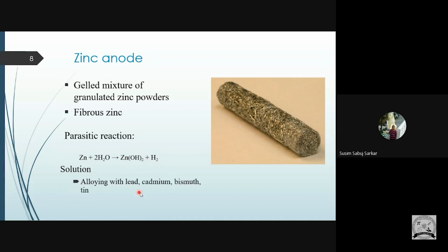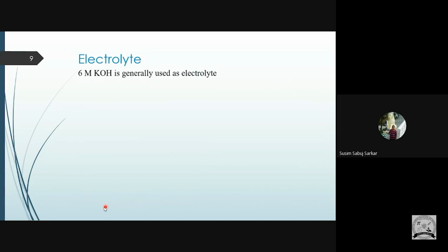The solution is alloying the zinc with lead, cadmium, bismuth or tin. This will reduce the parasitic reaction, because instead of zinc, the lead, cadmium or bismuth will prevent this parasitic reaction. Or sometimes we can coat it with, say, aluminum oxide or lithium boron oxide. In that case we can prevent the oxidation of the zinc and the production of hydrogen, so we can stop this. Now the second thing is the electrolyte: generally 6 molar KOH is used as the electrolyte.